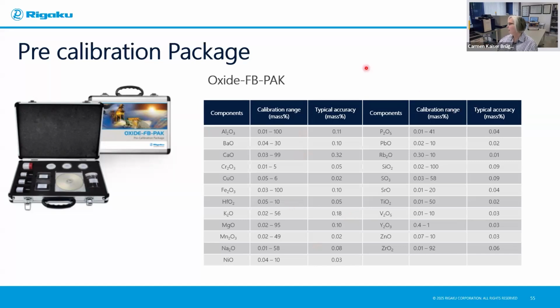So why do we have the wide range calibration? Well, this is to characterize all our raw materials that we have and the clinker and the cement, of course. Yes. So many different ranges are present in those different materials, and therefore we need the wide range calibration. So with this wide range calibration, you can see the analytical range for all the oxides, ranging from alumina to zirconium, and the accuracy that can be achieved on this analytical method.